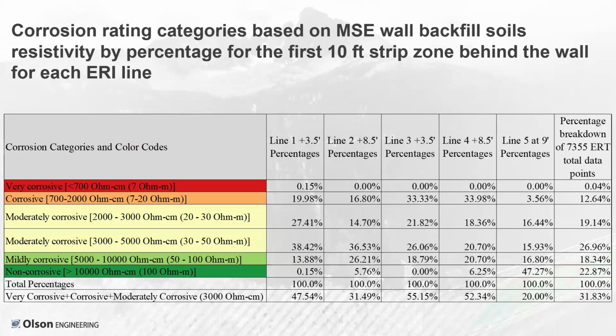So as you look at those percentages, there's not much that was very corrosive, only less than 0.1%. Around 13% of the total area tested in this 10-foot zone closest to the base of the wall, at 3.5 and 8.5 feet up from the base, and including the top of the wall, you can see that it was in a greater amount, particularly going through that. Typically at the base of the wall, it was fairly high as well. So that's not just the de-icing salts. Those are somewhat the conditions of the soils. The backfill is originally placed. The upper part can be influenced by the de-icing salts much more so. And then again, moderately corrosive from 2,000 to 3,000 ohm centimeters, predicting anywhere from 16% to 27%.